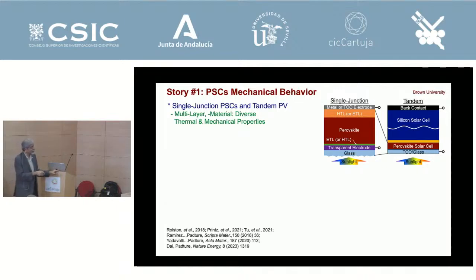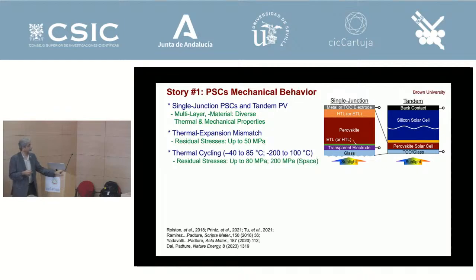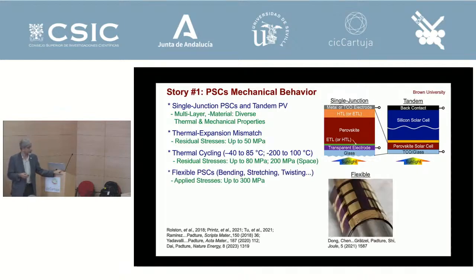So anyway, you have multiple layers, and they have diverse thermomechanical properties, and therefore you end up with residual stresses that can be as high as, say, 50 MPa, megapascals. And thermal cycling, these have to be tested from minus 40 degrees, so it's like Siberia, to 85 degrees, that's Andalusia, right? And then in space, it's minus 200 to 100 degrees Celsius, so that range is huge in space thermal cycling. So the stresses can be even higher, 80 MPa up to 200 MPa in tensile stresses. And then if you make flexible solar cells on plastic substrates, the stresses can be even higher, about 300 MPa, right?